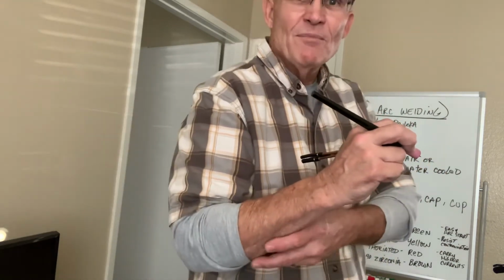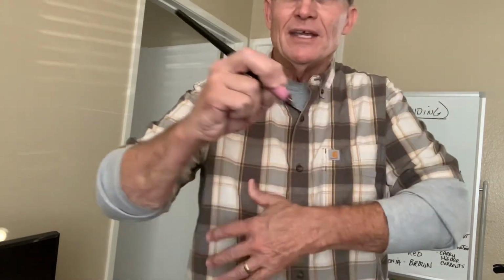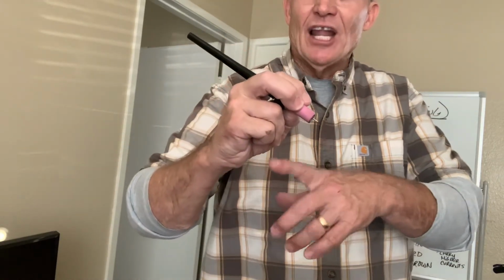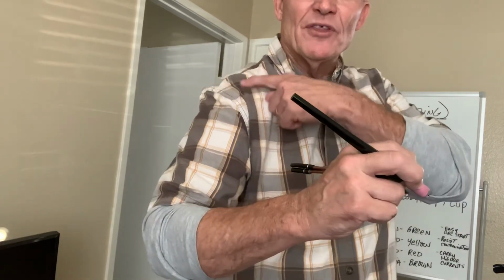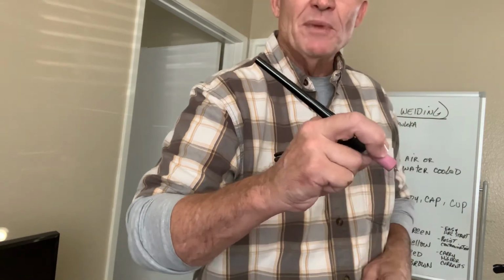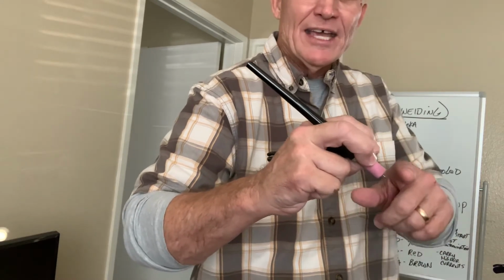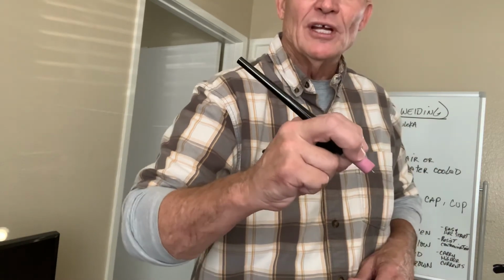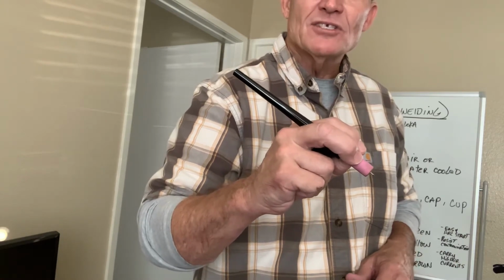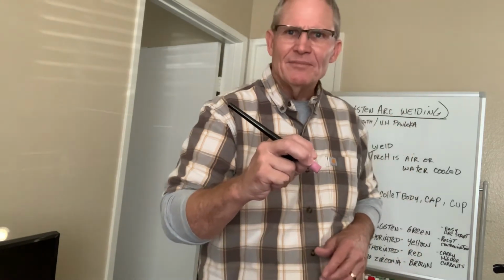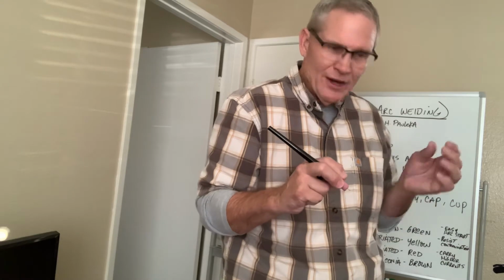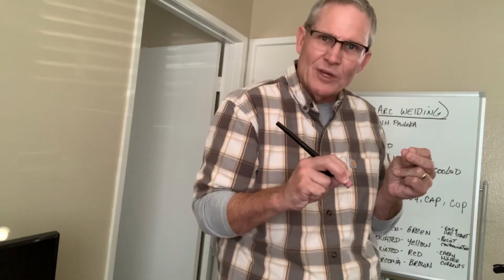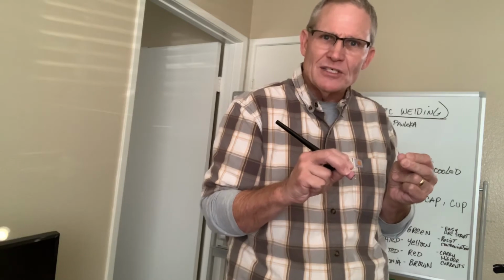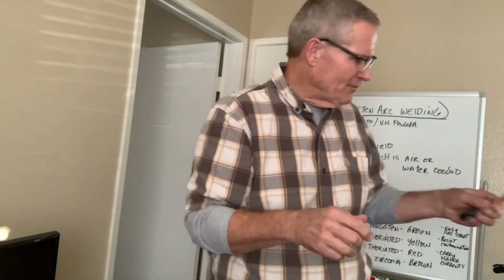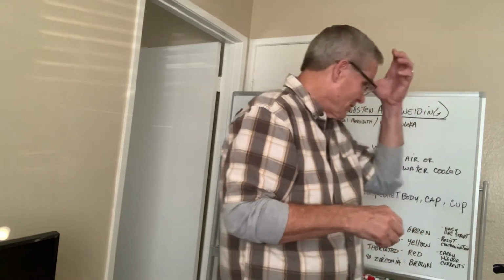Keep in mind, if I move this elbow away from my body like that, I get a lot more leverage on this torch. Now this is my pivot point up here, which means just the slightest movement, I get a lot of movement at the end of the torch. And with gas tungsten arc welding, I want to minimize that. And so my elbow goes against my body and I'm right here. It's very precise. I usually have a filler rod as I'm doing this, but I do the weld in a very precise way. So that's kind of an introduction to the torch itself.